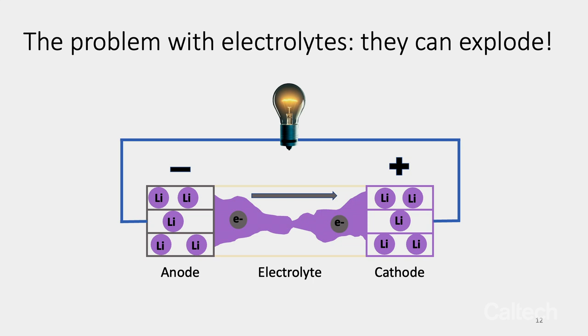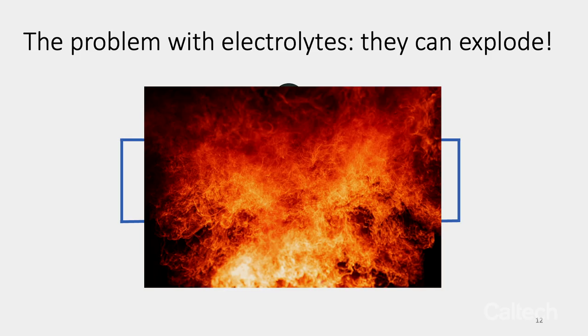Over time, they can grow and grow until they meet across the inside of the battery. A thing you should know about this lithium is that it's actually metal. If these dendrites grow sufficiently to connect across inside of the battery, inside the electrolyte, they actually provide a mechanism for the electrons to just go directly across the inside of the battery because metals conduct electricity. When this happens, all that energy that we've been dissipating by powering some external device gets discharged all at once through the inside of the battery. This generates a lot of heat. The electrolyte is generally made from liquid-like materials that are very flammable, not too dissimilar from gasoline. They're organic molecules. A lot of them come from the same sources. They're not as reactive, but given enough heat and energy, they can combust in much the same fashion. Then we end up with these explosions, much like the ones I showed you earlier.